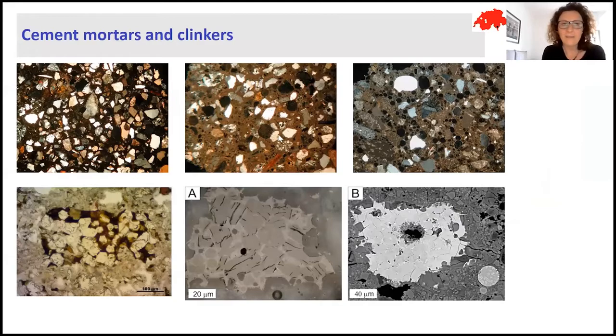And these are some images of cement mortar. You can see there are not so many differences. So it is very important to study, for example with the scanning electron microscope, these clinker residues. For example, in this image, you can see here these little black spots. So I need higher magnification or another mode of visualization, for example the reflective mode in bright field. As in this case, I can recognize these clinker residues and also characterize a cement mortar.